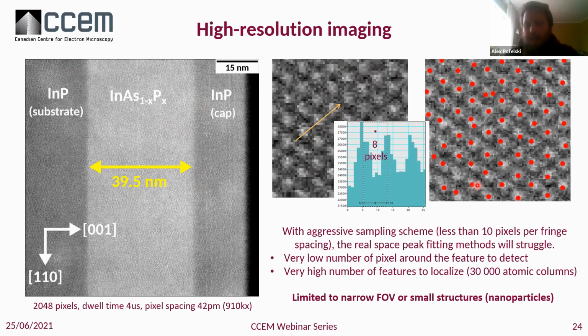And when you have an aggressive sampling scheme, the real space fitting method starts to really struggle because there are just a low number of pixels around the features. It makes it difficult to find them. In addition, the more you increase the field of view, the more you increase the number of atomic columns. So it looks like these real space methods are not very suited for this type of data, where you're still in high resolution mode but with a slightly larger field of view.